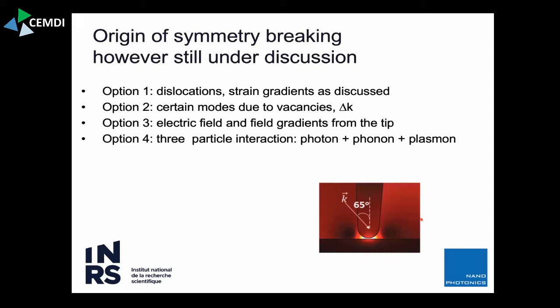So this is option number one I presented to you. So this is dislocation, strain gradients, surfaces, surface effects, surface modes, and so on. There is an option two, which is that if you introduce vacancies, you get local vibrational modes. They carry some momentum, and so you can go shopping for some additional modes in the Brillouin zone that you would normally not be able to access in the center of the Brillouin zone.